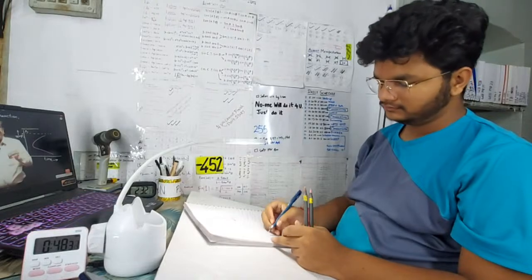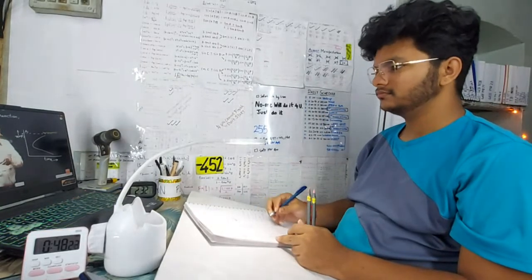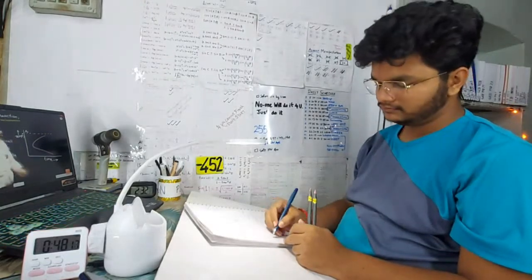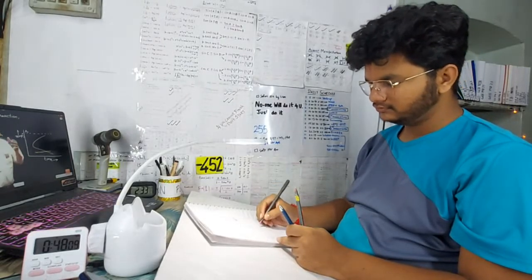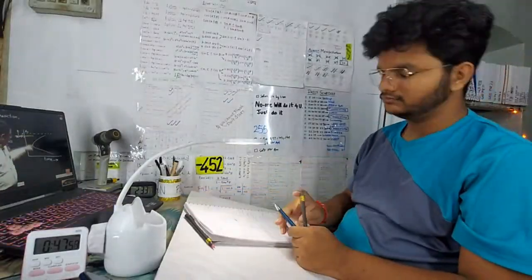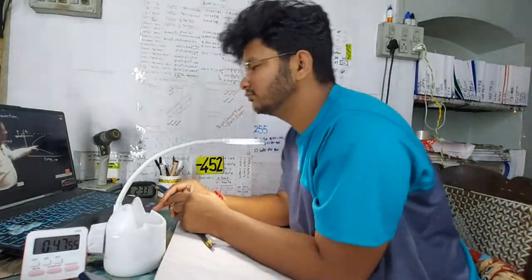Now, whatever the TTT diagram is going to come, that TTT diagram is also having temperature on the y-axis and time on the x-axis. That is, the TTT diagram is going to give you the time for transformation at a particular temperature. So time, temperature, transformation diagram. Here also there are three, this one is indicating transformation, temperature and time. So the upcoming TTT diagram, time, temperature, transformation diagram, looks exactly like this. Initially, the TTT diagram will decrease in time and then it will increase in time. So the shape of the upcoming TTT diagram, son, will be like this, and its basis is given by this particular graph.